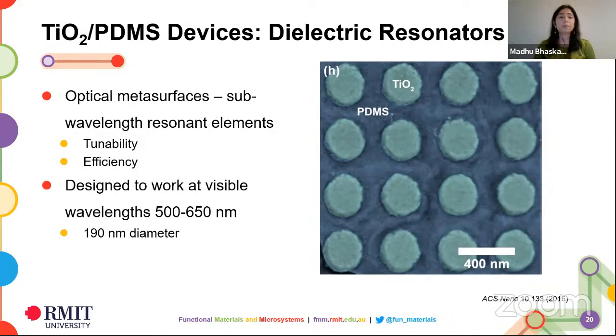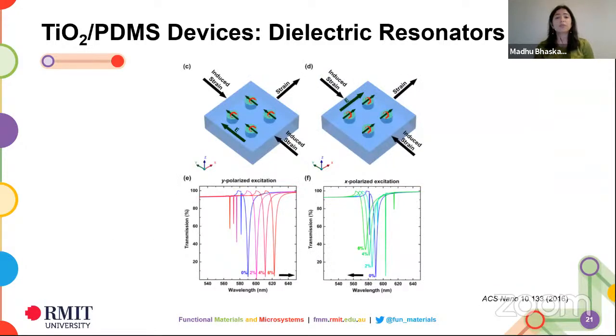Normally you use metals to make metasurfaces, but obviously metals have very high loss, and so efficiency becomes a problem. The other key thing which you would like metasurfaces to have is tunability. And the fact that it sits on PDMS offers mechanically tunable options for these dielectric resonators. So these devices were designed at Adelaide, and they found that if you change the polarization of the light impinging on the sample, and change the strain being applied on the material, you can switch the optical resonance of your sample. So you can get either a red shift or a blue shift in your optical resonance, just based on the amount of strain you're applying and by changing the polarization of the light which you're exciting the sample with.